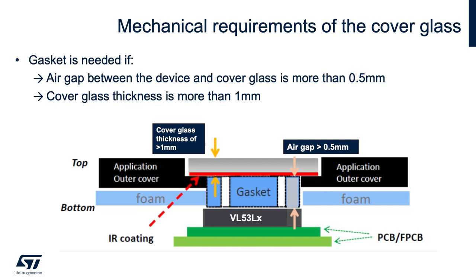Another thing to consider to reduce crosstalk is a gasket. A gasket can be made of foam or rubber, and it's placed on top of our device. You put hole openings in the gasket, so essentially the gasket is touching the top of our part and it's touching the bottom of the glass. And essentially the photons are then guided through these holes to leave the device and come back only through these holes, by which we're reducing crosstalk, as crosstalk can be caused from the photons coming out of our device hitting the glass and bouncing back to our device. By having the gasket in between the transmitter and the receiver, this can reduce crosstalk dramatically. This also helps in situations if you need to have an air gap more than 0.5 millimeters.